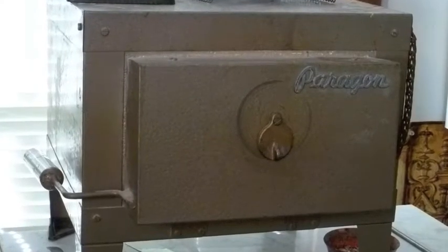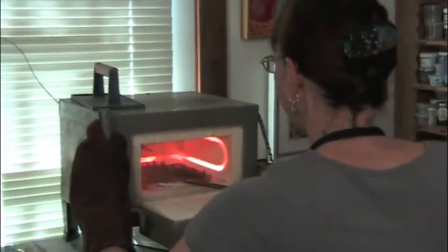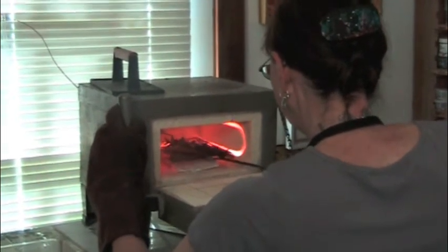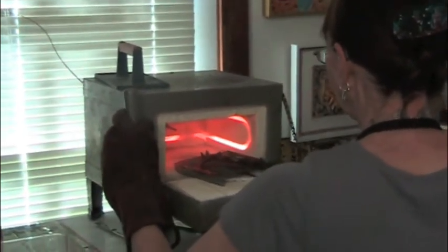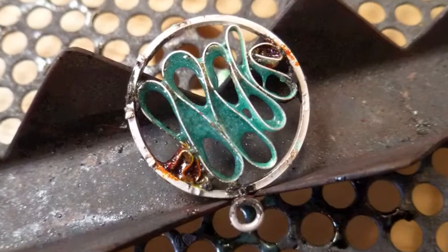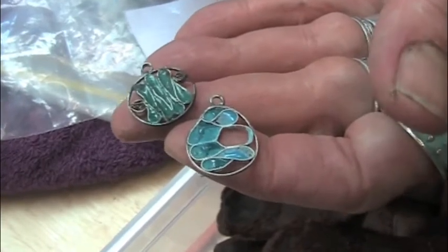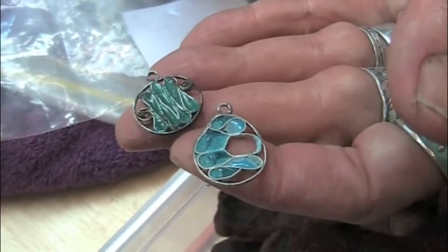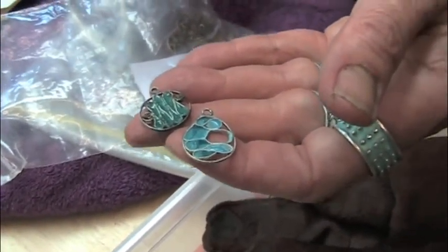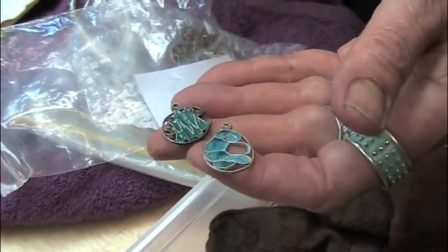Valerie taught us to dry them but I don't bother. It seems by the time it hits it in there, it's dry. There it is. You continue to complete filling the holes until it's a complete film with those short firings — 40 seconds, 50 seconds. Then once it's a complete film with absolutely no pinholes...